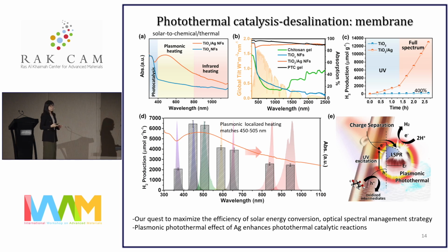In order to validate the role of the plasmonic nanoparticles in this enhancement, we have used various monochromatic light sources with different wavelengths to study the hydrogen production. And you can see that the plasmonic localized heating of the hydrogen production matches very well with the silver resonance band at 450 to 505 nanometers. Basically, this confirms that it's the plasmonic photothermal effect that has indeed enhanced the catalytic reaction.